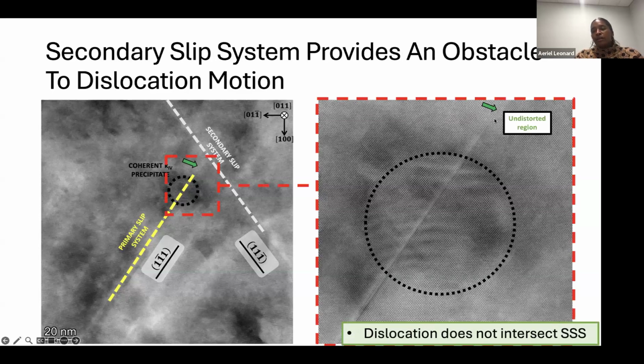And the region here is really undistorted. So it lets us know that that dislocation does not intersect the secondary slip system, and that there's some interaction between the stress fields of those dislocations that's preventing that transmission. And so again, we're starting to see some of the hardening mechanisms that are occurring at these early stages of loading in the material.